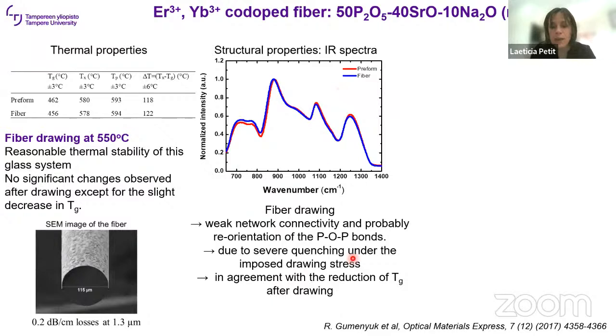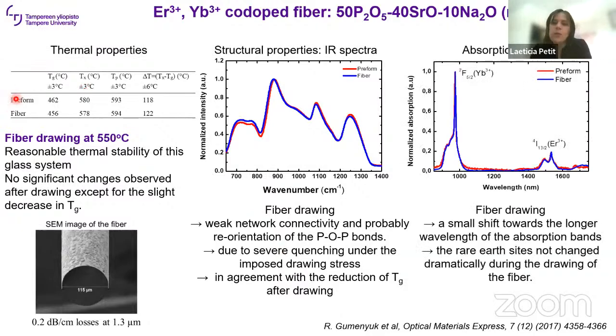And what we think is happening is we have just some reorientation of the POP bonds, and that might explain the small changes in the thermal properties of the glass. And then we look at the absorption property of the glass before and after the drawing. And this reorientation of the POP bonds has no impact on the rare earth sites. And so that confirmed that we can actually draw this glass into fibers.